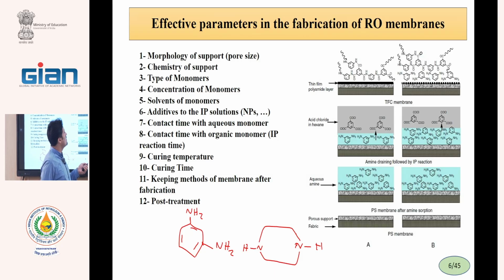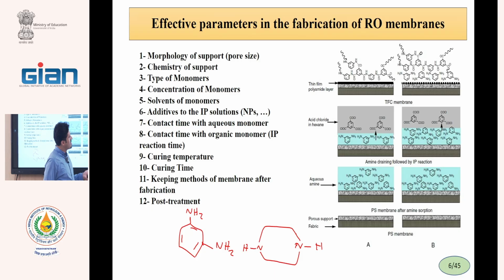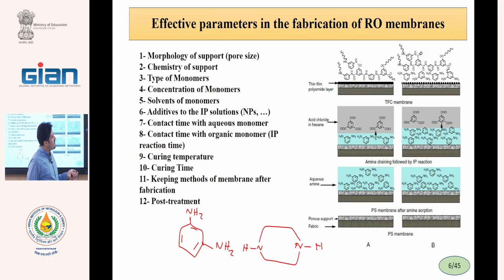The morphology of the support is very important. Chemistry, concentration of monomers: this slide shows the effect of concentration of MPD, that with increasing MPD concentration, we have a very rough surface and very low carbonyl groups. Therefore, with change of the concentration, the properties of this thin layer can be changed. The kinetic and thermodynamic are very important. There are many papers and books that discuss the kinetics of interfacial polymerization. The solvent is important. We use hexane, heptane. Contact time is important. In industrial scale, we want to reduce the contact time.